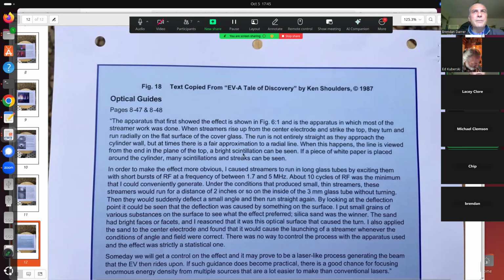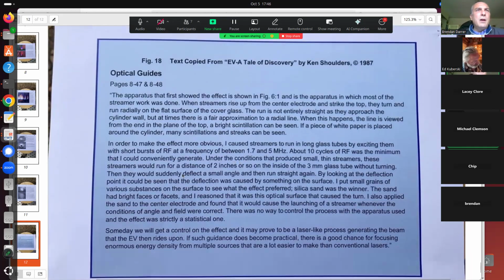A bright scintillation can be seen. If a piece of white paper is placed around the cylinder, many scintillations and streaks can be seen. In order to make the effect more obvious, I cause streamers to run in long glass tubes by exciting them with short bursts of radio frequency at a frequency of between 1.7 and 5 megahertz. About 40 cycles of radio frequency, RF, was the minimum that I could